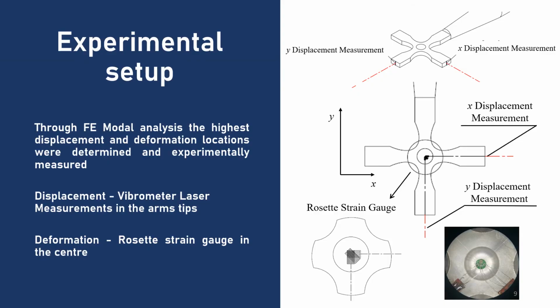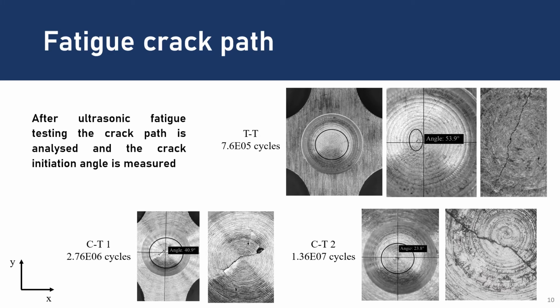Now the followed experimental setup is very similar to the uniaxial tension compression ultrasonic fatigue machine. Instead of measuring just one displacement, we measure two: the vertical, as we call it, direction, the Y displacement measurement, and the X displacement measurement. We also made strain analysis where we measured the strain in the fatigue testing region using a rosette strain gauge in the center of the cruciform specimen. From the experimental setup, the cruciforms were applied to the ultrasonic fatigue machines and tested until failure.